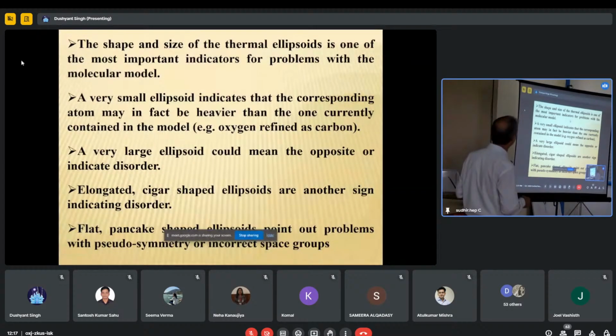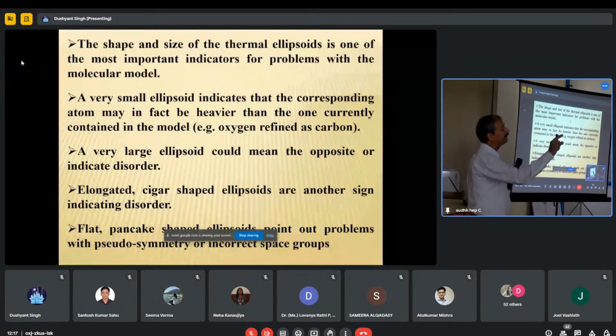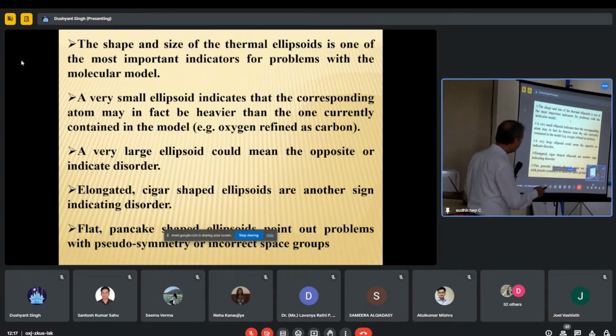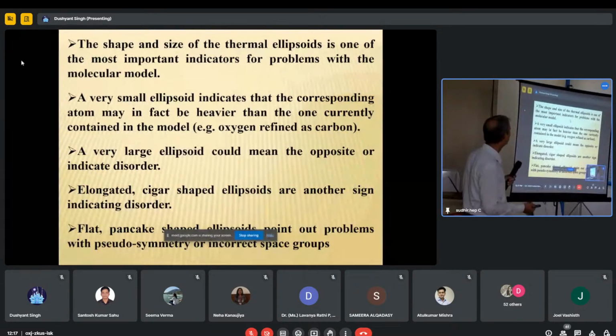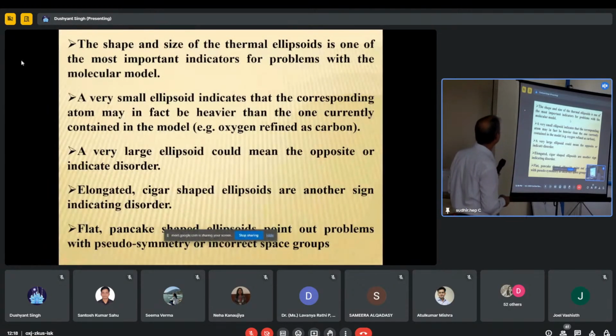The shape and size of thermal ellipsoids is one of the most important indicators of problems with the molecular model. So what kind of disorder is present? A very small ellipsoid indicates that the corresponding atom may in fact be heavier than the one currently contained in the model. Suppose we have refined oxygen as carbon, your ellipsoid will become very, very small. In a ring, you will see 5 atoms showing almost the same size ellipsoid and one very, very small. So you immediately come to know that you have put oxygen as carbon, and vice versa. If it is carbon and you give it oxygen, then the size of the ellipsoid will increase. Elongated cigar-shaped ellipsoids are another sign indicating disorder.